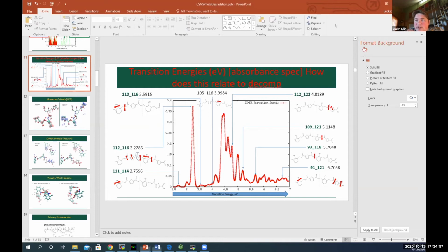There is a comment from myself. It's not a question, but in some sense, I'm answering you. The spectrum that is demonstrated on this slide is an absorption spectrum which corresponds to very low intensity excitation, for absorption of only one photon. While decomposition happens if one picks a transition energy where we have a peak in absorption and communicates more and more photons at this energy. So it is not a literal connection. If you have just the absorption spectrum and submit one photon, reactions highly likely will not happen. We select the transition energy at which the polymer is able to accept energy, and then we send more and more photons there until it decomposes. So absorption and decomposition are not equivalent.